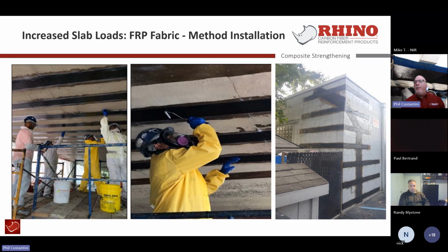And again, we came up with an application for a corner wrap using unidirectional, so this is regular cured material, to reinforce this area, and then subsequently the added material that would go over top of that, because it's an outside application, would be a waterproofing material, a UV protected coating like an acrylic coating that can go over top of it to basically UV protect the epoxy, not the carbon fiber. The carbon fiber is inert, it's UV stable, but we need to protect the epoxy because that is the bonding agent in any application that's an exterior repair.